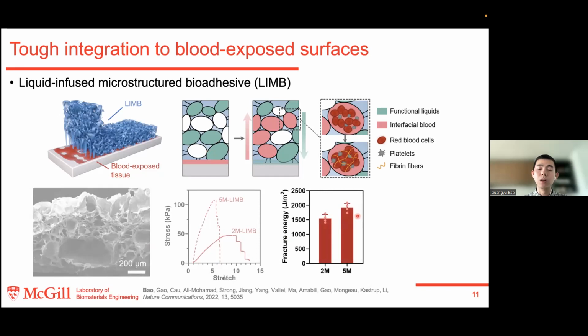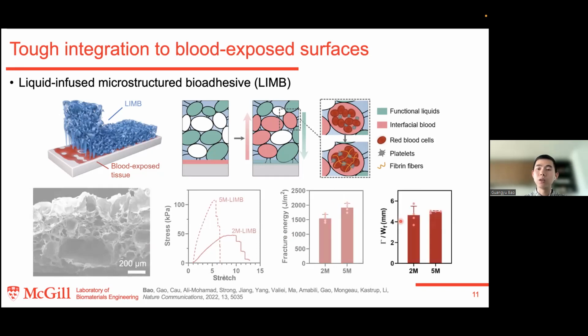It's very similar to, or even exceeds, most of the soft tissues in the human body. And here, we calculated its pore sensitivity, which is around 5 millimeters, which means that any defect smaller than this range will not be sensed by our adhesive matrix. And considering the pore size within our matrix is a couple hundred micrometers, which is significantly lower than this value, the porous structure within our matrix does not affect its mechanical property.